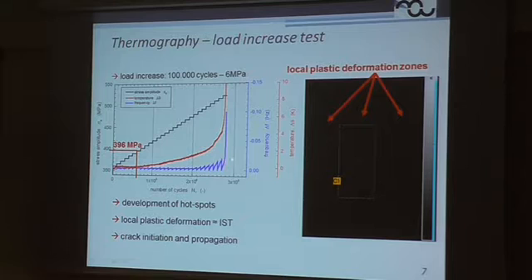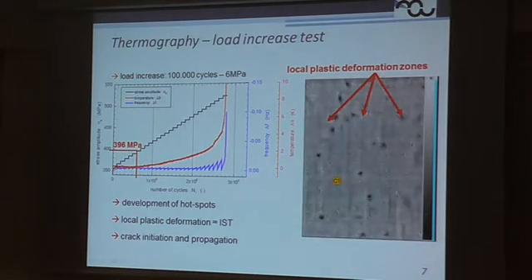So what we see here is that the first change in resonance frequency can only be observed after 2.2 million cycles, and we correlate this with the macroscopic crack initiation and fatigue crack growth. But regarding temperature change, we see a much more sensitive feedback signal, and I want to show you a small video. Hopefully it's working.